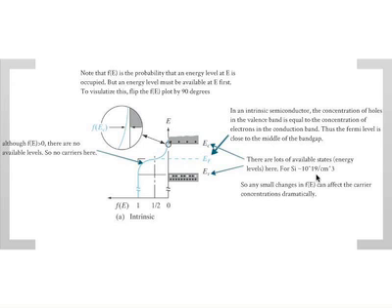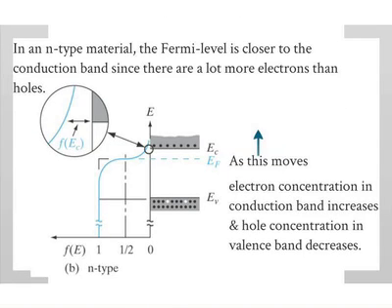What that means is that any small changes in probability here can make a huge change in the carrier concentrations because you have so many levels available. Orders of magnitude. So that's why this Fermi-Dirac distribution is extremely important for all devices. In fact, when we talk about transistors and so on, we'll draw the Fermi level. We'll try to qualitatively understand what's going on, so you need to understand this conceptually now. Any small changes in the f of E by temperature or whatnot can make huge changes in the carrier concentration.